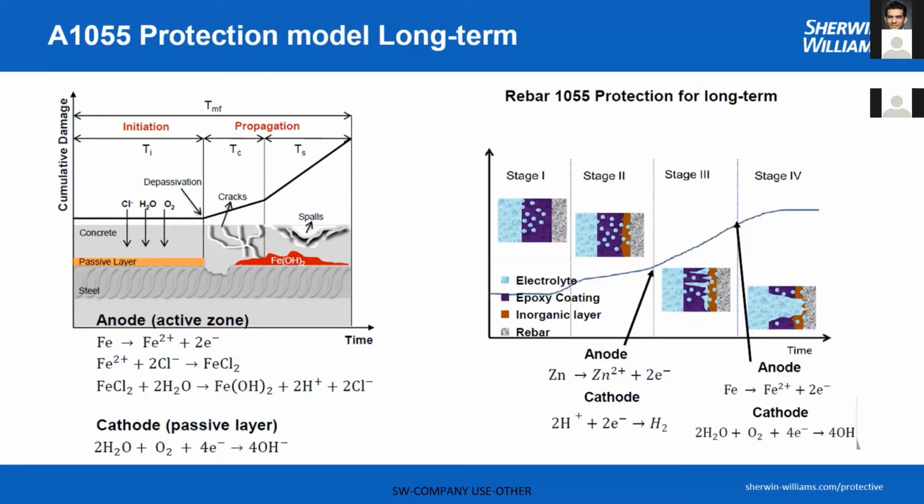So again, we're getting the corrosion resistance of the barrier coat, but if we do have a break in that barrier coat, now we have the galvanized or the zinc layer to take us home to a longer life cycle. So for those who are familiar with the old Z-bar technology, this system performs similarly in theory. However, the zinc layer is thicker and less porous and has better formability. And additionally, this system can be provided by multiple suppliers to the end customer, which obviously would be the DOTs.